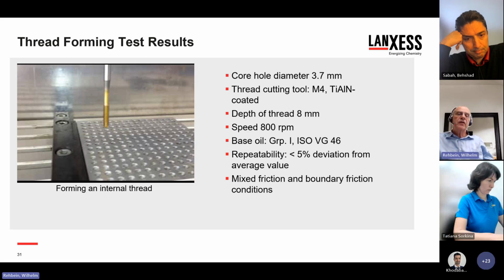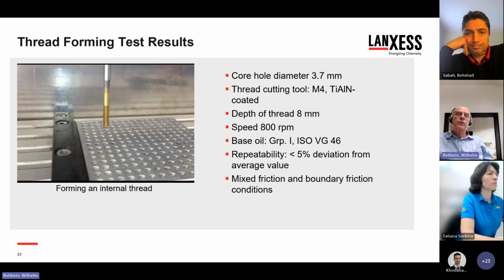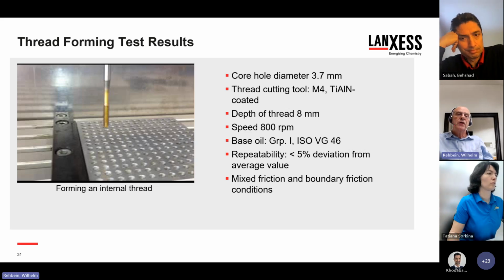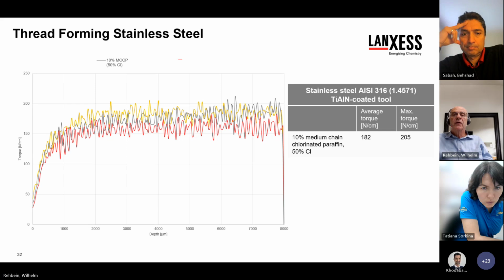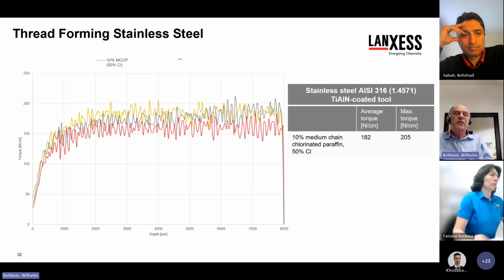In this test series, the core hole diameter was 3.7 millimeter. It was also an M4 tool, but it was titanium aluminum nitride coated. The depth of the thread was 8 millimeter. The machining speed, again, 800 RPM, and we used the same base oil as for the thread cutting tests. So again, we started with stainless steel and with a 10% medium chain chlorinated paraffin formulation.